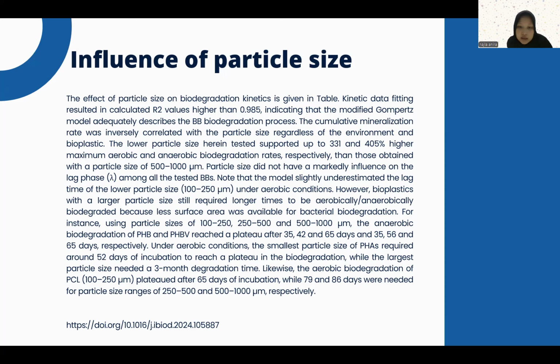Under aerobic conditions, the smallest particle size of PHAs required around 52 days of incubation to reach a plateau in the biodegradation, while the largest particle size needed a 3-month degradation time. Likewise, the aerobic biodegradation of PCL 100 until 250 micrometers plateaued after 65 days of incubation, while 79 and 86 days were needed for particle size ranges of 250 until 500 and 500 until 1,000 micrometers respectively.